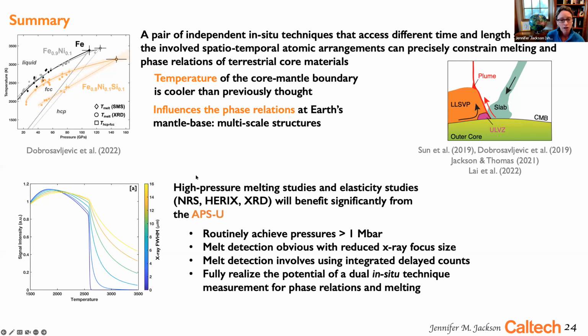And so looking forward, high pressure elasticity studies will benefit significantly from the APS upgrade. We can routinely achieve pressures above 1 megabar. Melt detection becomes obvious with a reduced X-ray focus spot size. This is a simulation I did for one of the melting runs. And we could fully realize the potential of a dual in situ technique measurement for phase relations and melting. And with that, I thank you, and I'm happy to turn it back to you, Barbara.